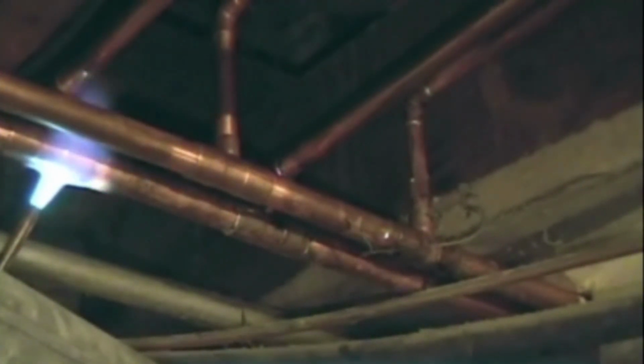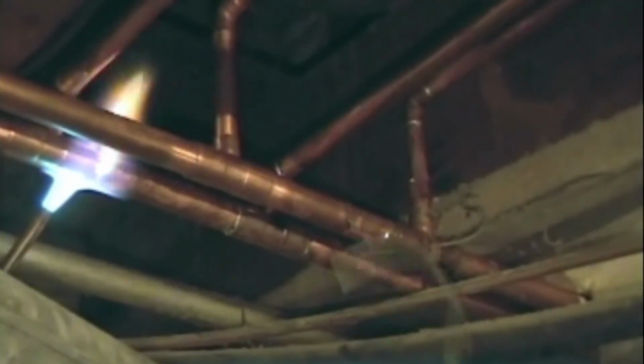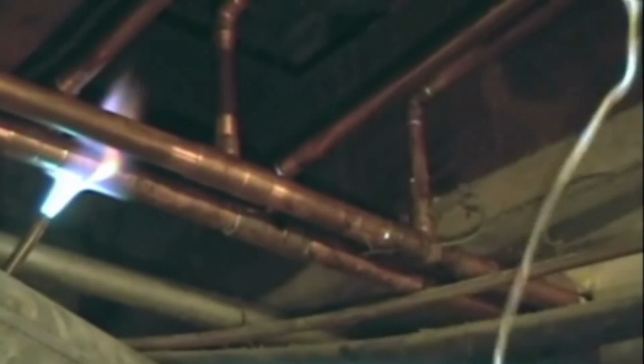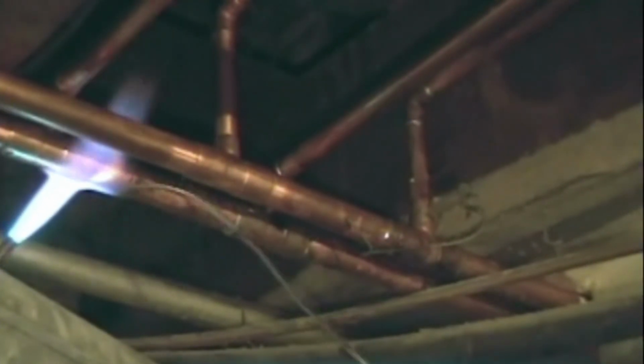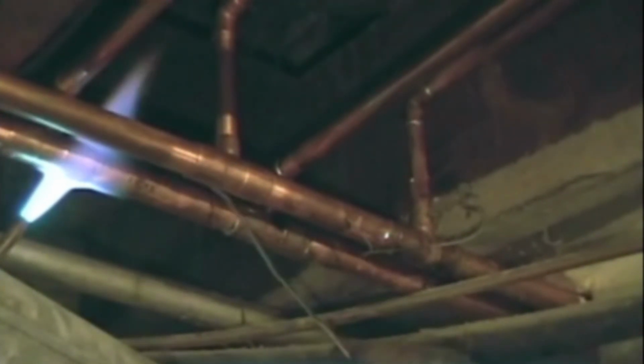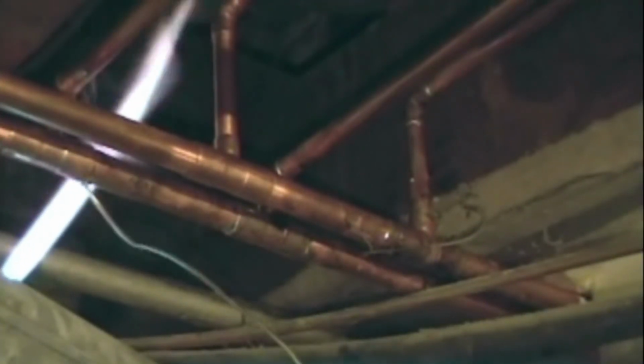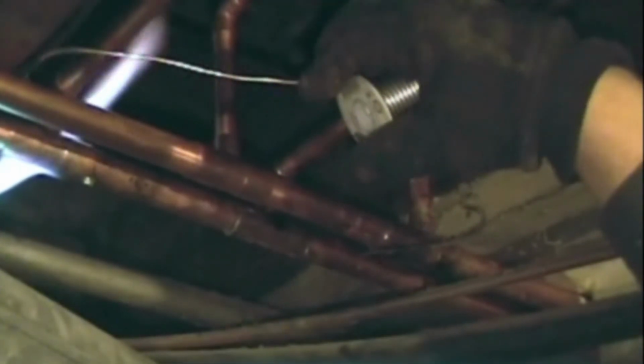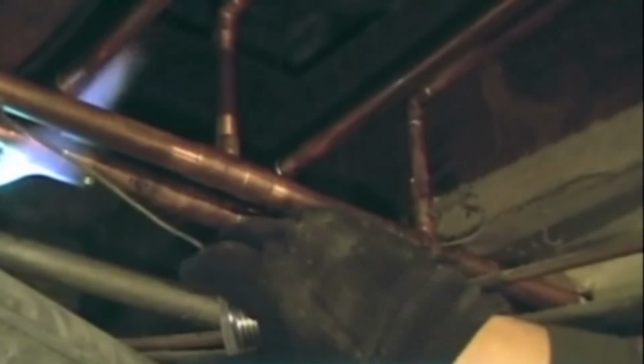Well, we established that the flux is a chemical barrier, right? Yeah, it's an organic acid paste. But it has a strict thermal limit. If you push the temperature of the copper too high, the flux doesn't just boil, it burns. It catches fire. It scorches and undergoes thermal decomposition. It carbonizes into a hard black scale inside the joint. Okay. And the moment the flux carbonizes, it loses all of its protective properties, the barrier drops, and the extreme heat instantly oxidizes the raw copper underneath.